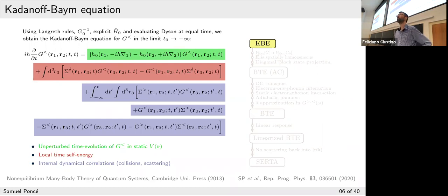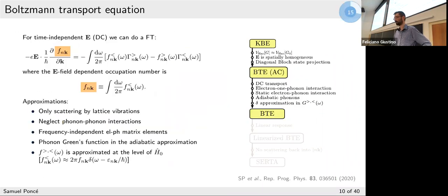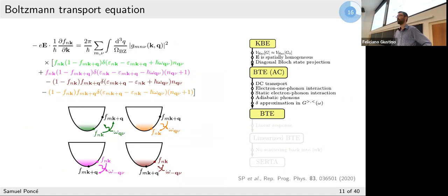Just wondering how the spin enters the calculation. I assume that the velocity and the scattering rate are spin dependent. Yeah. So basically, currently you can, for example, use spin-orbit coupling. That's not an issue. But you cannot at present do magnetism. I mean, in theory, you could. There is no issue. The only problem is that you would need to compute the electron-phonon matrix element, which is both spin resolved and also with magnetic effect, for example. And this could be done in principle. It's just that it's not implemented, at least in Quantum ESPRESSO, with magnetism.